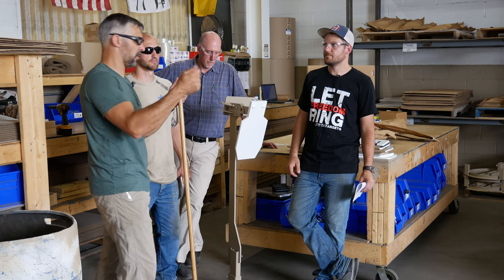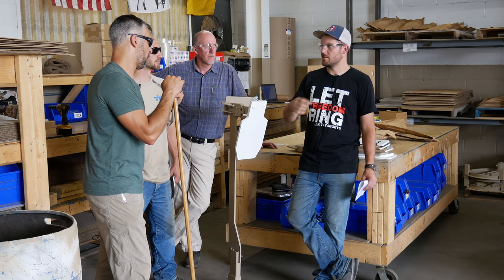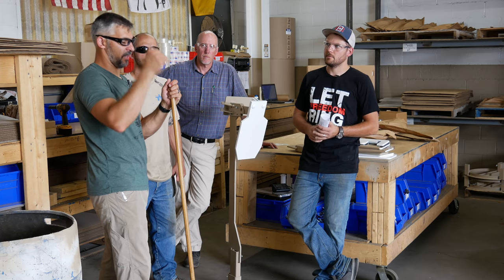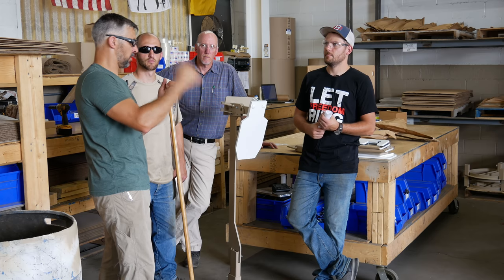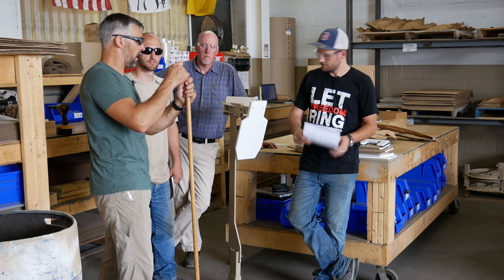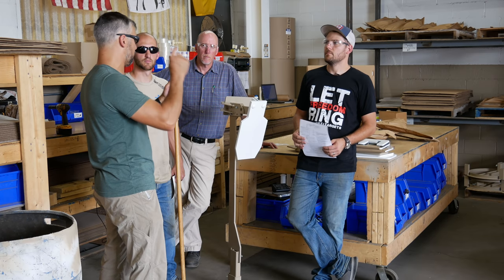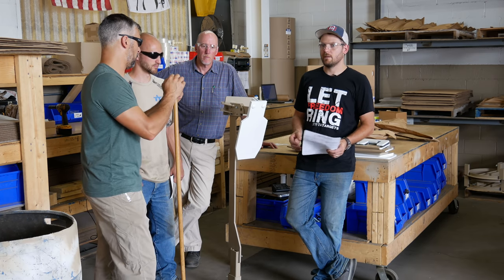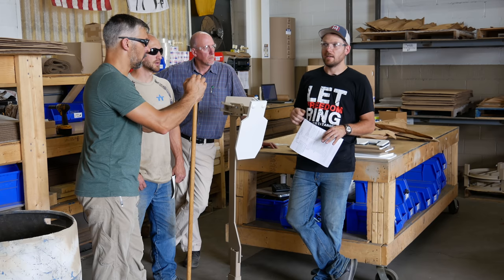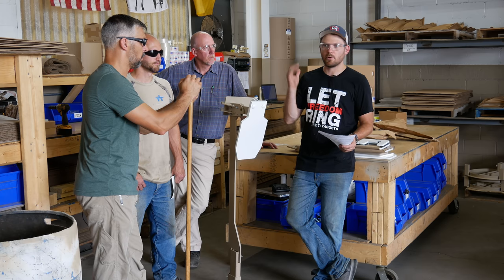It's like taking a steel hammer and just beating steel. You're looking at velocity and the size of the bullet. The smaller the bullet and the faster it's going, the more prone to damaging. All right, so you want to use a projectile that's not made of ferrous metals. Yep. And you can test that with a magnet. You can take a heavy magnet and put it on the bullet tip if you're not sure. And then speed. So if I go with 5.56 or 6.5 Creedmoor or one of these fast moving small bullets, speed's a problem. Yes. All of our distances we've calculated and tested with ammunition that's 3,000 feet per second at the muzzle. It's very easy with 5.56 NATO especially to get XM193 that's coming out at like 3,400 feet per second.